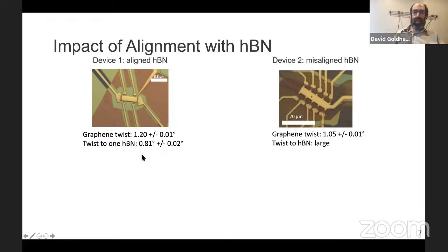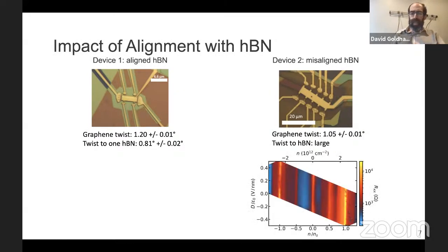Later on, we made many more such samples, and this is a case where we intentionally did not align the boron nitride. So I'm just going to compare the data from the two. In the case where the two are not aligned, I've now mapped the data into a space that makes more physical sense than gate voltage. This is the displacement field on the vertical axis, the field normal to the plane, and the density on the horizontal axis. And I've also changed to natural units for density, where 1 means we've completely filled the moire band.